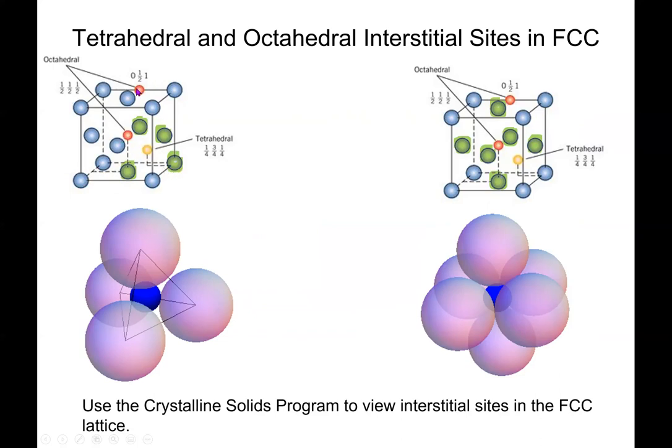And then they've got a couple of other atoms, impurity atoms, that are located in between sites. So there's one that's directly in the middle, and I'll talk about that one in just a second over here. We've got one sitting on this edge. Okay, so that represents a type of site that could be any of the edges. And we've got one that's sitting here that we've seen before in the diamond cubic structure, the zinc blend structure. That's sitting off of this atom by a quarter, quarter, quarter in terms of its location. And this one is the one that is in a tetrahedral site. So if I take this corner atom and the three faces, neighboring faces, we will find that these three form a triangle. They're all touching. And this one's sitting on top of them, also touching. And so here's our picture.